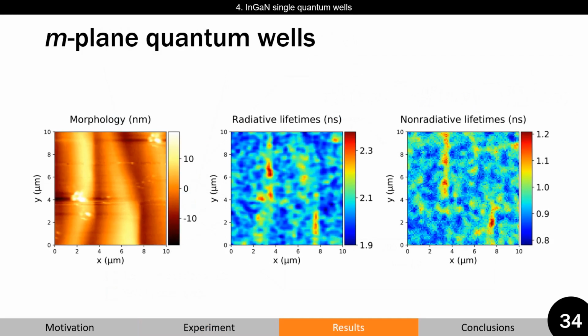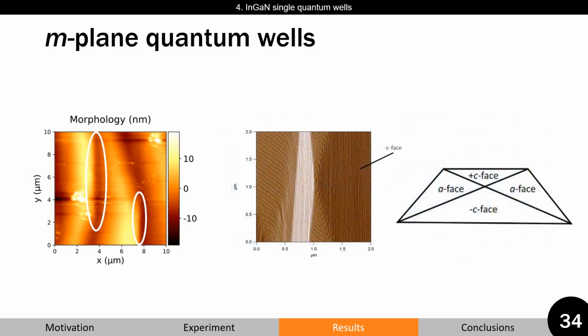This is an example of one of the studied samples, a white M-plane. One can observe two things. First, both types of lifetimes are not spatially uniform. Second, one can observe areas with prolonged lifetimes, which seem to correlate with surface morphology. M-plane quantum well surfaces are known to be contaminated with pyramid-like hillocks. This is a high-resolution AFM map, and this M-plane is non-polar, but when these defects, pyramid-like hillocks, are introduced, different faces facing different polar crystallographic orientations are formed.